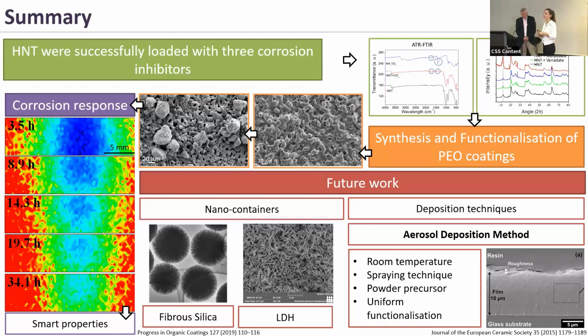If it's okay, I've got one follow-up question. In terms of it being wear resistant as well, is the principal protection mechanism you're looking for when the coating is mechanically broken that you want them to activate? One of the reasons for which I want to do this type of functionalization on ceramics is that the ceramic matrix will provide this wear resistance, while the smart functionality will provide corrosion protection simultaneously. So I don't really think that the encapsulation of inhibitors will play a fundamental role on the wear response. I think the ceramic matrix will be responsible for the high wear resistance.